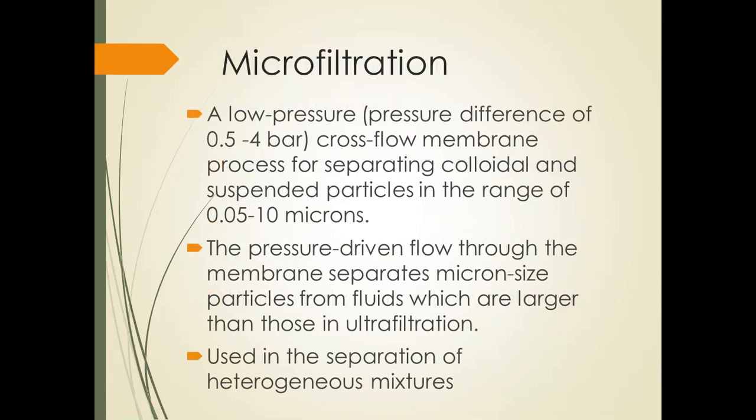Now let's go to microfiltration. This is a low pressure, cross flow membrane process, with a pressure difference of only 0.5 to 4 bars, for separating colloidal and suspended particles in the range of 0.05 to 10 microns. The pressure driven flow through the membrane separates micron size particles from fluids, larger than those in ultrafiltration. This is used in separation of heterogeneous mixtures.